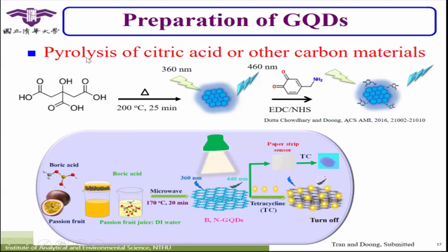Okay, so we can do the pyrolysis of citric acid or other carbon materials. Here is one kind, citric acid. Citric acid has three carbons, one, two, three. If two citric acid molecules combine, they can form a benzene-like structure. So they are quite easy to form zero-dimensional graphene quantum dots. We just use a temperature of 200 degrees C for 25 minutes, and they can form.